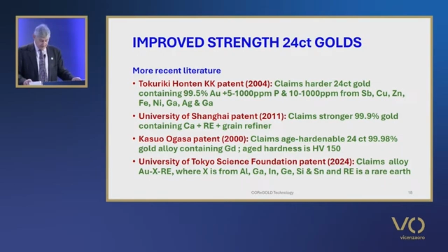A Chinese patent claims a stronger 99.9% gold microalloy containing calcium and a rare earth element plus a grain refiner, while a 2000 patent by Ogasa claims an age-hardenable 24 karat 99.98% gold microalloy containing gadolinium that reaches a hardness of about 150 Vickers after aging.